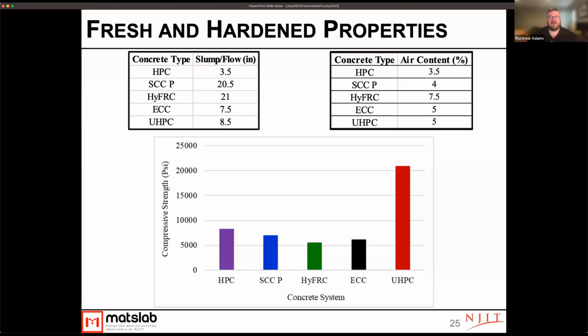The big thing I want to note here is, particularly for the HPC and SCC, we had relatively low air contents. We really had trouble air entraining these mixtures in the lab. If any of you are familiar with labcrete versus field concrete, air entrainment is really a bear in the lab to get right. And unfortunately, this was done during COVID, and we should have switched to a different air entrainer to try to get better air entrainment, but procuring materials during the height of COVID was basically impossible most of the time. And so keep those air contents in mind, because they do affect some of our results. And we hope to someday have a chance to rerun some of these tests for the freeze-thaw damage.